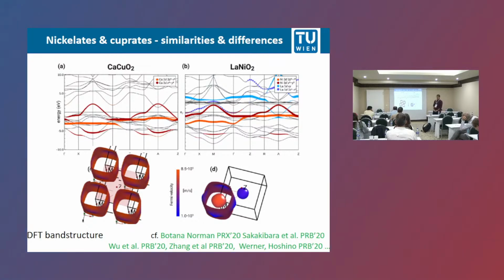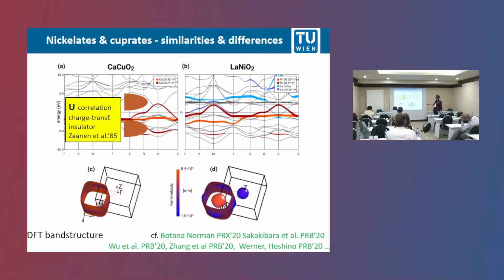Now that is the weakly interacting picture. Now if electronic correlations come into play, this x²−y² orbital splits into 2 Hubbard bands. And then for the cuprates, it is such that the oxygen orbitals are closer to the Fermi level than the lower Hubbard band. And because of that, if you hole dope the cuprates, you get the holes into the oxygen. So cuprates in the Zaanen-Sawatzky-Allen scheme are a charge transfer insulator. Still, a Hubbard model can be used as an effective description, but with some working around to justify it.